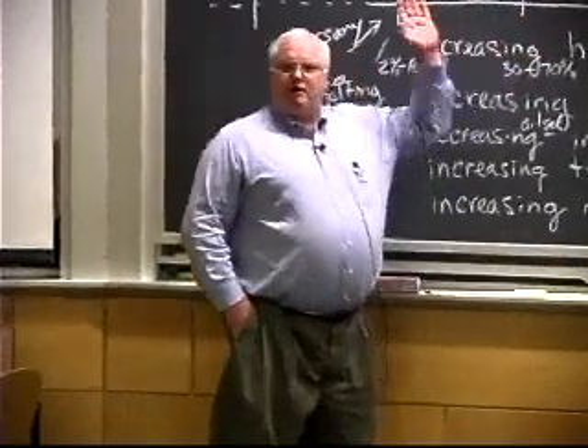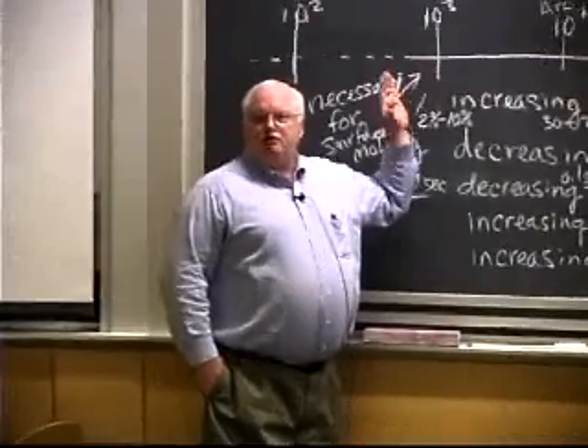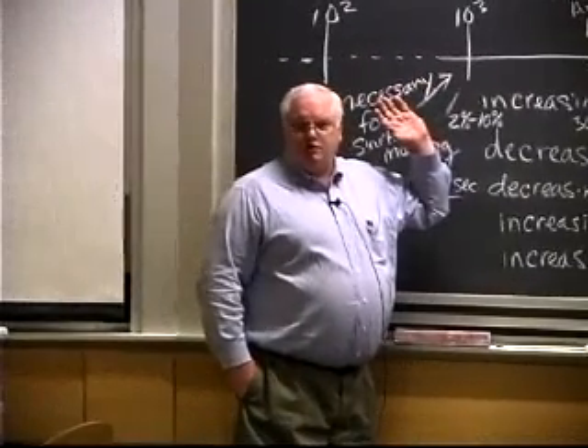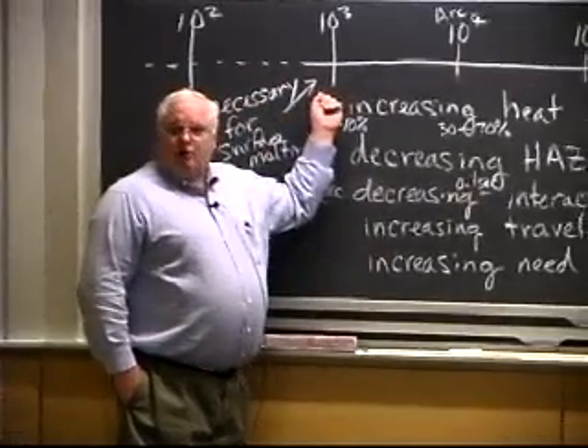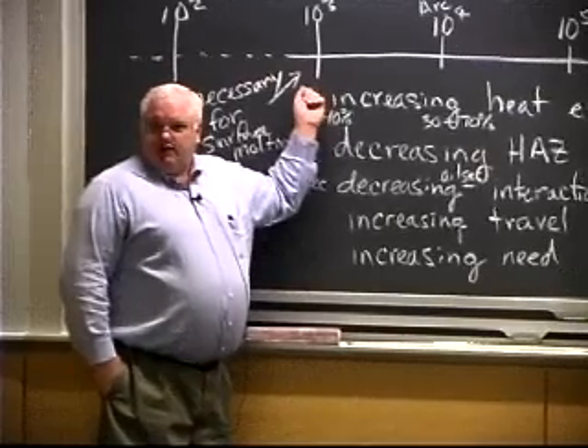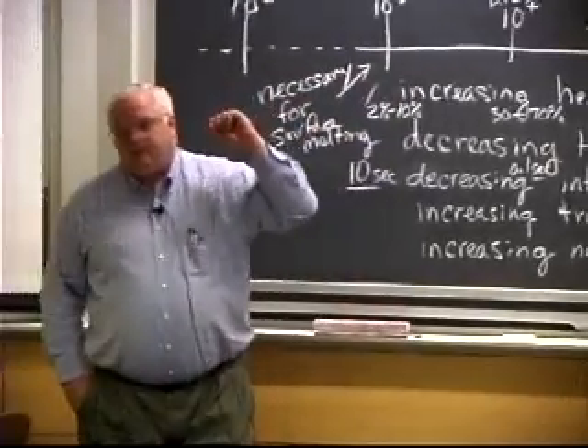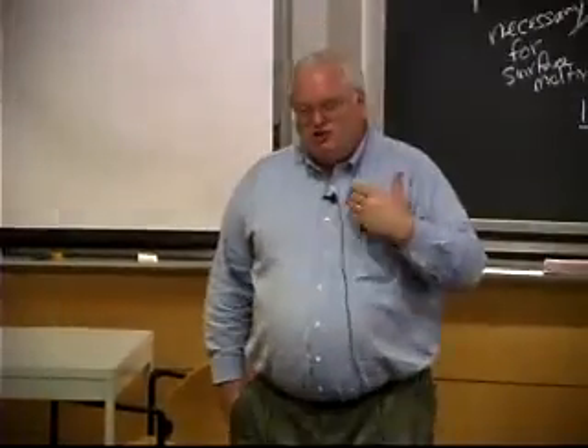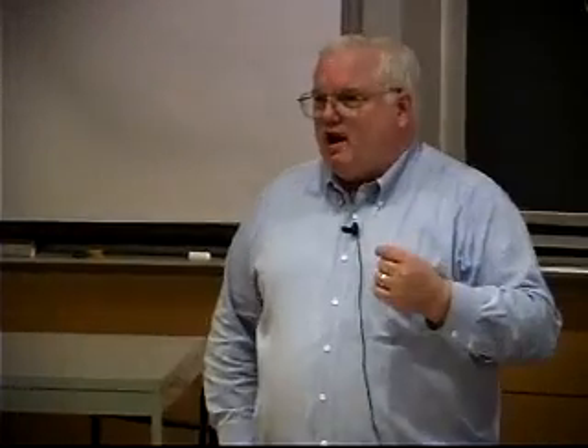But if you go over here to Wentworth Institute, where they will give you a 2-year course in how to weld or a 1-year course, you'll always start with Oxy-Acetylene, which is at 1,000 watts per square centimeter. The reason is the interaction time for the weld puddle in Oxy-Acetylene is on the order of several seconds. So what a welder is doing with the heat source, they're moving that torch around to control the weld puddle. They're trying to fill up a seam.